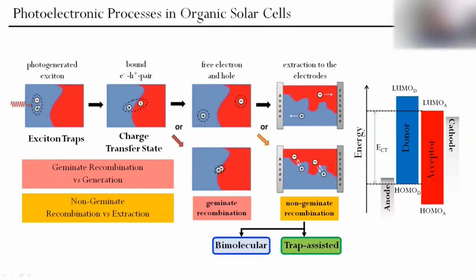this photogenerated exciton can diffuse for a very short distance before they annihilate, recombine. It's about 10-20 nanometers. So that's why morphology of this nanocomposite mixture of donor and acceptor materials in the active layer of organic semiconductors is a very critical parameter. If we have two big domains of donor and acceptor material, it will cause a problem, because our photo-excited electron hole pairs will not diffuse until the interface and will recombine before.